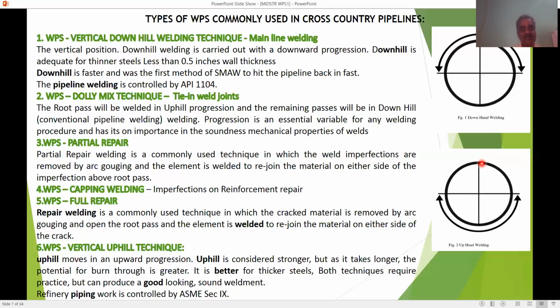Number 5 WPS, the fifth WPS, is full repair welding. Full repair means any imperfection observed in the NDT testing, specifically radiography and ultrasonic testing, in the root pass. The specific area is marked on the pipe and excavated completely up to the root pass. Remove the weld metal and reweld the re-root pass and other passes as per the WPS full repair procedures.